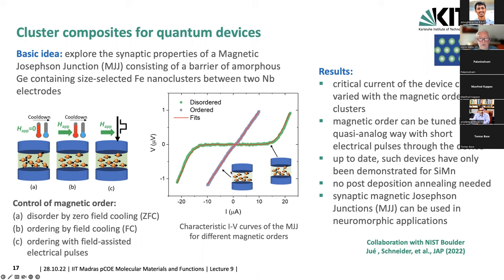But what they have also shown is that with a very small electrical pulse, which you send through these superconducting niobium electrodes, you can induce ordering as well. And this allows you to change the properties of the film by an electric pulse. And this is important to use it in that application. So this was a very first work and collaboration, but we are continuing on that. This has been published recently in the Journal of Applied Physics. So if you're interested, you can read more about it.